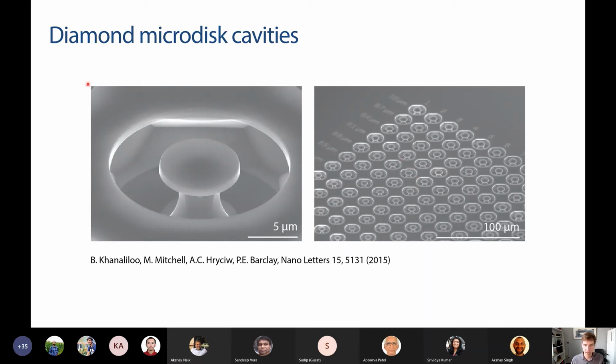Of course, it's nice to have a high quality tool which can be more reproducible and these kinds of things, but there's no new exotic fabrication tool that we've needed to use to do this. And the etching chemistry just relies on oxygen plasma, so we're not using any special gases really for doing this.